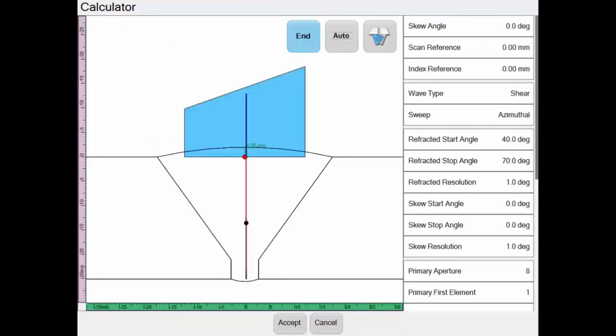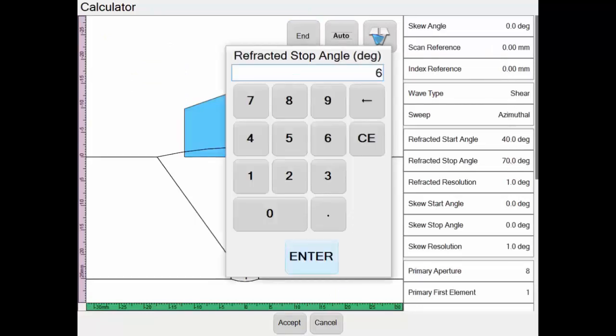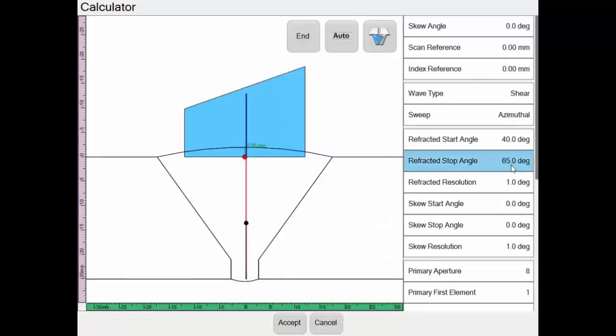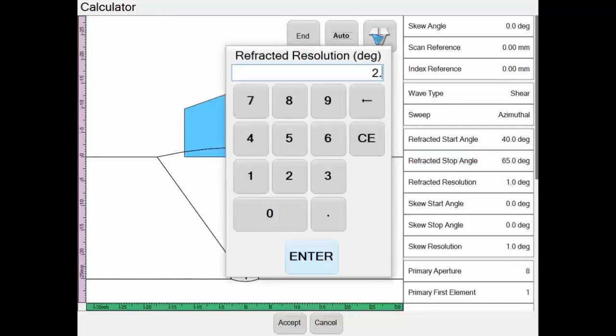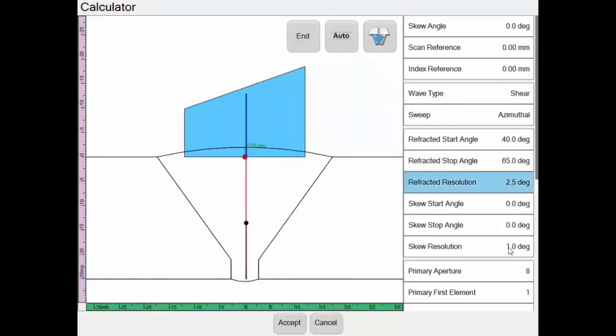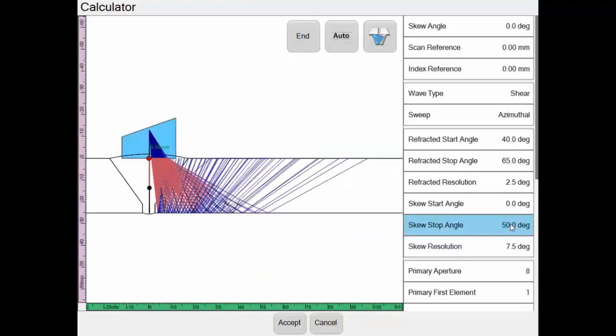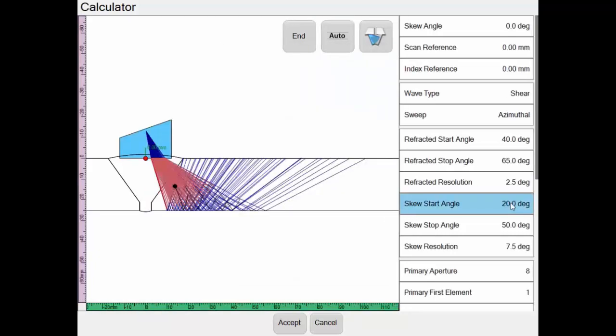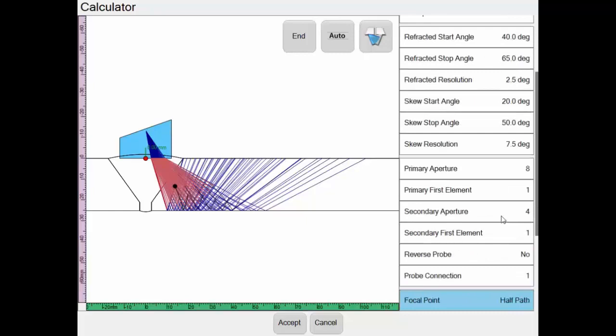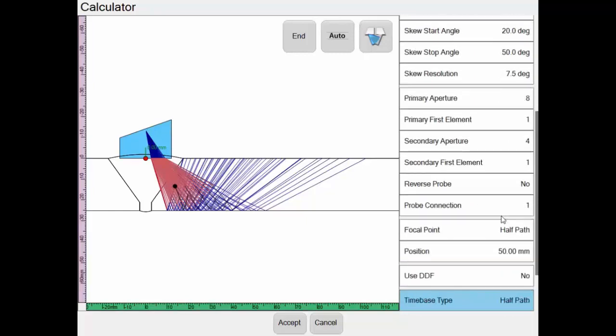Depending on the frequency and the size of the individual elements of the array, the probe assembly can generate shear wave beams with refracted angles between 40 and 65 degrees, and skew angles between 20 and 50 degrees relative to the scan axis orientation. Typically, more than 50 acoustic beams are fired at each probe position.